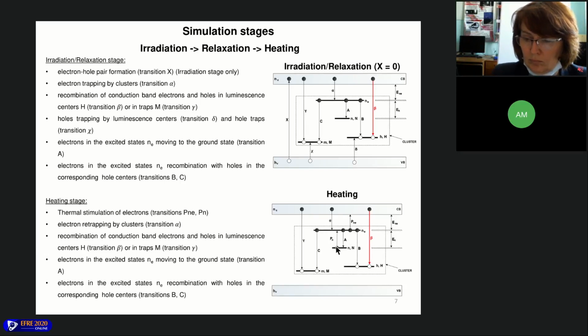Electrons in the ground state can move to the excited state, NE, transition PN, and reach the conduction band, transition PNE. During this stage, electrons also can recombine with holes in hole centers inside the same cluster. Conduction band electrons can be retrapped by cluster, recombine non-radiatively with holes in deep hole traps, and recombine with holes in luminescence centers radiatively. The number of radiative recombinations per time unit stands for thermoluminescence intensity.